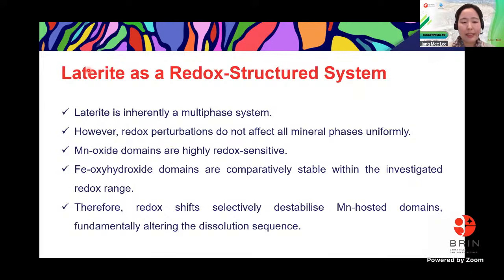Laterite is, as you know well, inherently a multi-phase system. It contains a lot of goethite or hematite, and manganese oxide, and the cobalt is co-associated with manganese and sometimes iron. However, redox perturbations do not affect all mineral phases uniformly. For example, manganese oxide domains are highly redox sensitive, because manganese normally exists in a 3+ or 4+ high valent oxidation state, while iron oxyhydroxide, mainly goethite domains, are comparatively stable within the investigated redox range. So the redox shift selectively destabilizes the manganese-hosted domain, fundamentally altering the dissolution sequence.